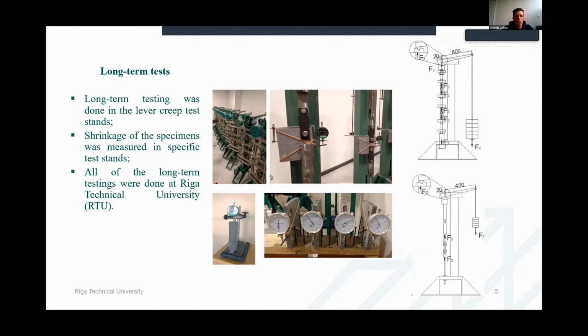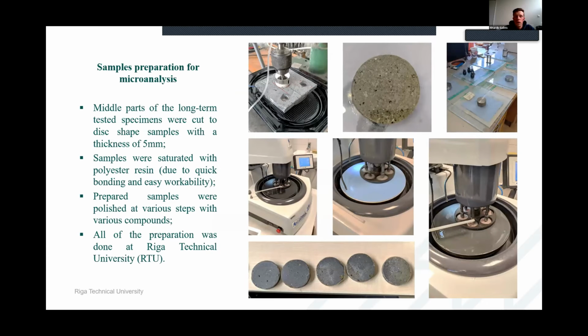Creep was tested in the lever test stands, as you can see in the upper images. On the right, you can see the schemes for these lever test stands, and shrinkage strains were measured in specific test stands. Both creep and shrinkage tests were done simultaneously in the same environment, in the same room, so that the results for these tests could be used together, and the data analysis would be done much more thoroughly. So when the long-term tests were done, the sample preparation for the microanalysis tests began.